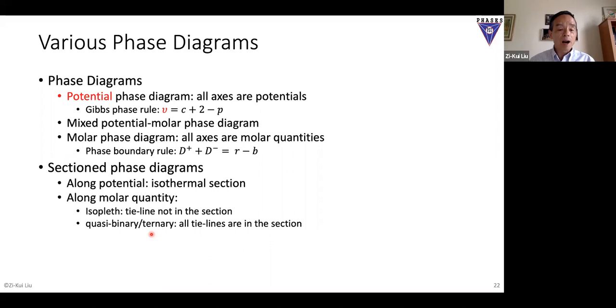That's very common in oxide systems. In that case, all the tie lines are still in the section. You cut it along the tie line. Cut along the tie line is the same as cut along potentials, right? Because the tie line represented by chemical potential means you fix chemical potential. So it goes back to this cut through sections through the potentials.